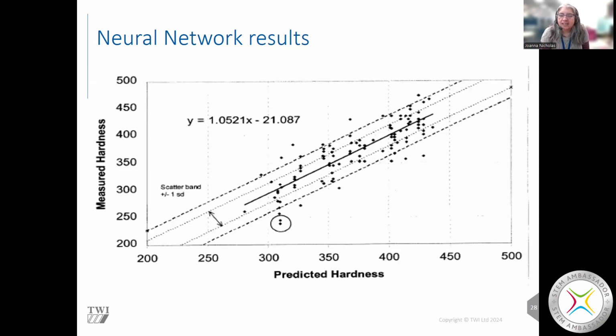For the neural network, using it outside of the test data was possible, but we had to put some boundaries on it. We said, well, how far can we push the composition, the different elements in the composition? The carbon equivalents, how wide could we be? So we allowed plus or minus 0.1 carbon equivalent at the extreme ends of what was allowed, because then we could be confident that we weren't straying too far out of what had been trained on. It's important to make that caveat, because we don't know whether the model would have that same relationship between hardness, composition, and thermal cycle for a different composition, because as we change the composition, the way that the thermal cycle affects the material changes. So if we go too far, for example, if we used a high chromium steel rather than a low chromium steel, would that make a difference?